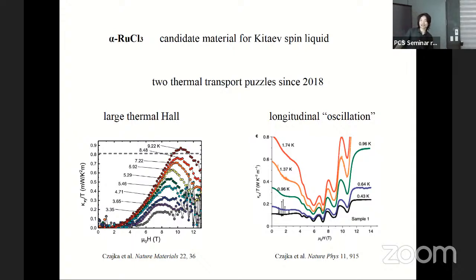Right. So you can see that these two phenomena occur at different temperatures. These start to ramp up above 4 or 5 Kelvin. And this effect is not shown in this picture, but this effect will go away above 4 Kelvin. So these are two different temperature regimes. But we find a connection between them. That is, in the magnon theory here and in the competing state theory proposed by us here, both of them need a very strong frustrated competing state. That part is compatible.